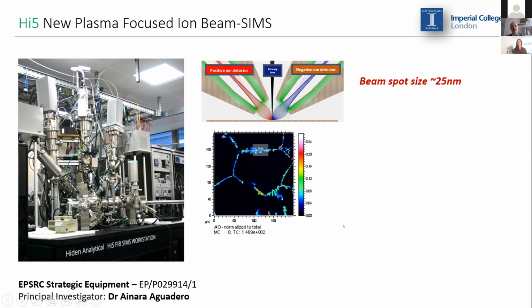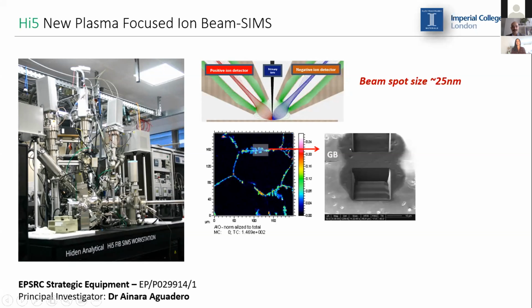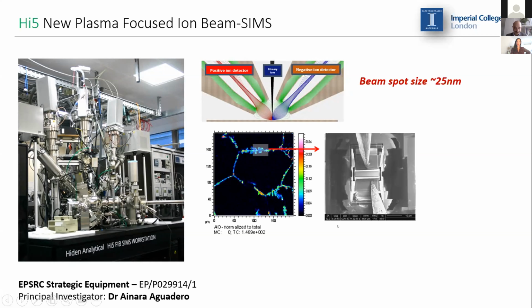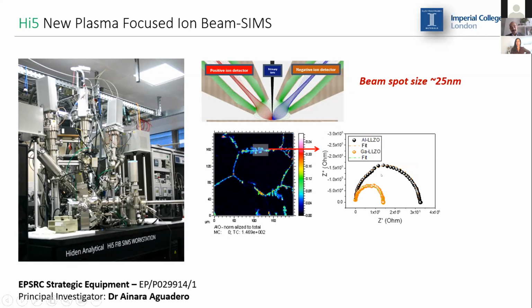And for instance, if we take advantage of the microstructure of our pellet, where we've got very big grains, we could perhaps start milling pillars which include a grain boundary, or mill a pillar in the middle of the grain, so we can also do an electrochemical impedance analysis much more accurate. So we can take into account just one grain boundary, two grain boundaries, and so on. That is something that we start doing.